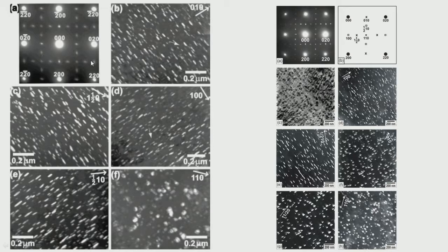So again, we did a similar analysis, but when we look from 100 as well as 110, we find that only the ellipsoidal precipitates are getting imaged. This gives an indication that this alloy contains only gamma double prime and not gamma prime. This is how one can get information. This I have taken because it is some personal choice from my work experience. I thought that this explains how to go about and analyze complex diffraction patterns and get useful information about the microstructure by analyzing this diffraction pattern.